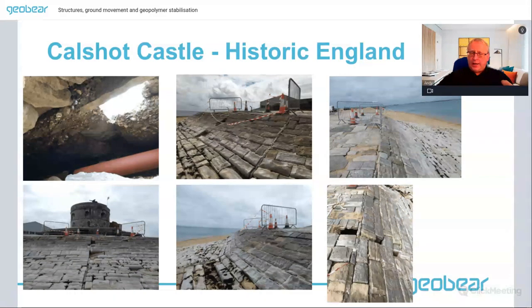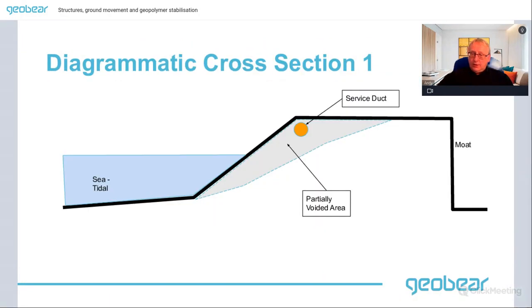Another one was on Calshot Castle, another Historic England job, a little bit further down the coast. And here we had voiding developing behind or underneath some stone slabs, which were part of the sea defences. So in cross section, we have this voided area shown right next to the sea. This was essentially a sea defence, and fines were being lost due to water coming in and out at high tide and washing fines out of the cracks in between the sandstone sets.